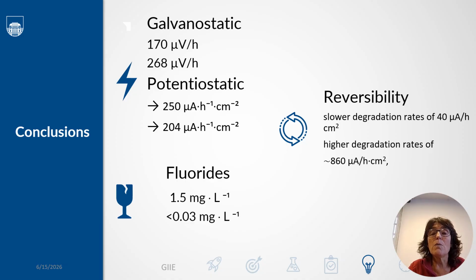Taken together, our results show that PEM electrolyzer degradation has a dual nature: a reversible component, mainly contamination and protonation effects that acid regeneration can recover, and an irreversible component that progresses regardless of the regeneration.